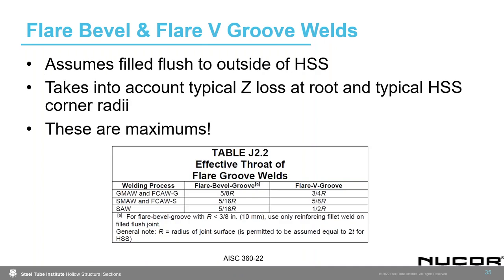These assume a weld filled flush to the outside of the HSS, and as I mentioned, it does take into account the typical Z loss at the root and a typical HSS radius. But what I want to impress upon you is that the numbers given in this table in the specification are maximums. So filled flush is not necessarily what we need to have everywhere. This is definitely a case where, if you don't need it to be filled flush in every single case, please put the effective throat that you do need in the weld symbol, and that will allow the fabricator to design accordingly. I have a fear that we put this weld symbol on all of our drawings when we don't necessarily need it, and it results in a lot more welding than we actually need for that joint, and we might be able to save some economies by actually specifying what is required.